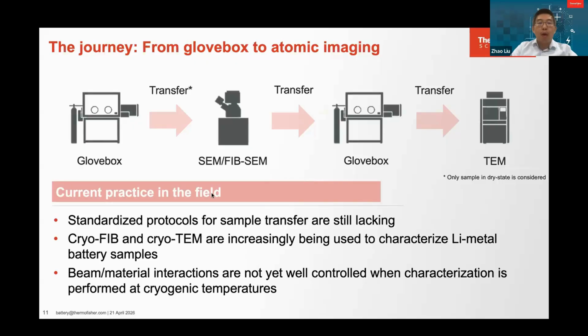So the question is, when you transfer between the different devices, how do you do the transfer, and in the different instruments, is cryo always needed? Currently, in practice in the field, both the transfer and the cryo conditions used in the instruments are not standardized, meaning that different groups use different protocols for the transfer and characterization process. That causes the results to be inconsistent or not even repeatable. We also see that although cryo-FIB and cryo-TEM are increasingly being adopted to characterize lithium metal battery samples, for example, they are not consistently used that way.